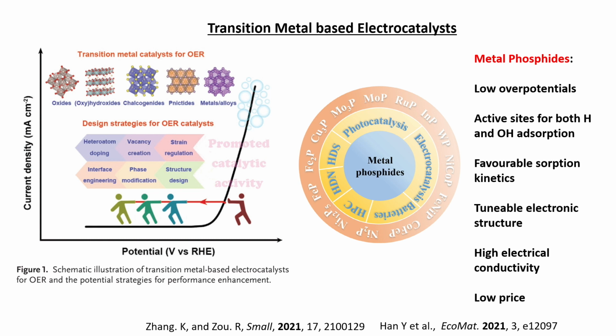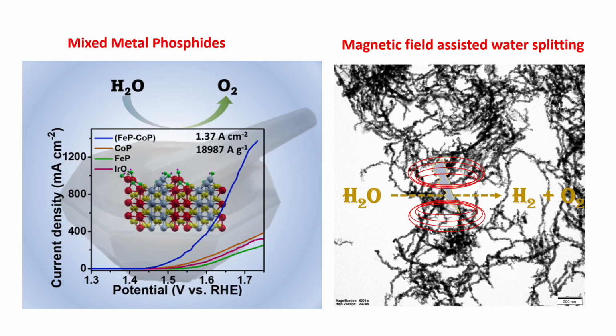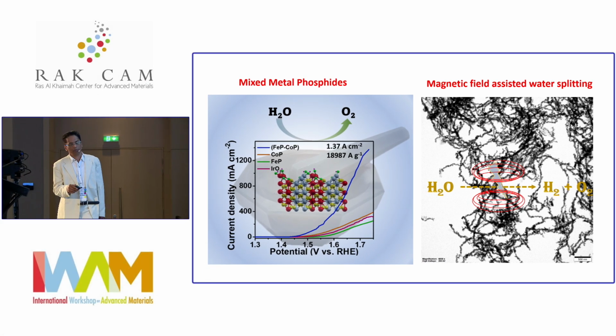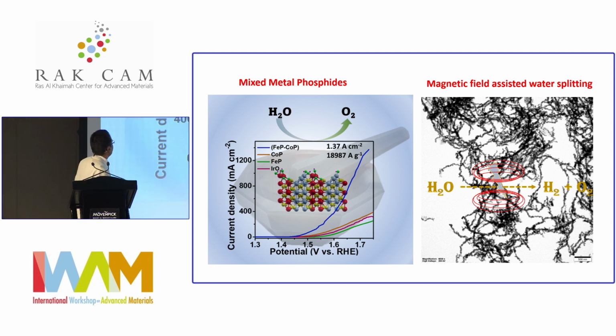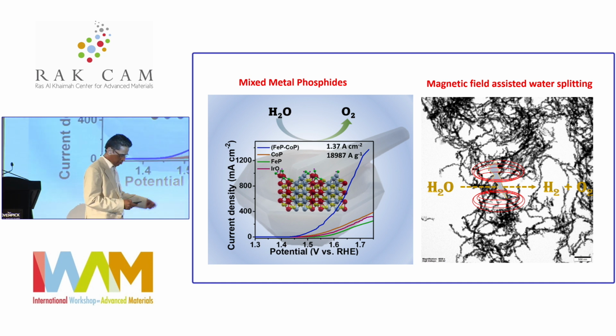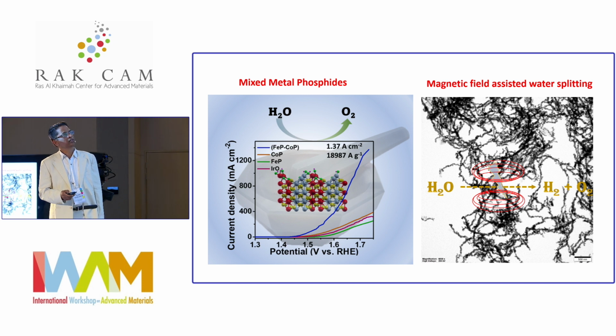Oxides have a problem, particularly conductivity issues, so metal phosphides are getting recent attention for their overpotential reduction, as well as active sites for both hydrogen and OH adsorption, favorable adsorption kinetics, and tunable electronic structure with high electrical conductivity compared to oxide materials. And again, it's low price. So I'll be touching upon the metal phosphide which we used for this. Here our strategy is based on the synthesis technique, and the iron phosphide, cobalt phosphide, and also oxides are produced by a borohydride reduction strategy.